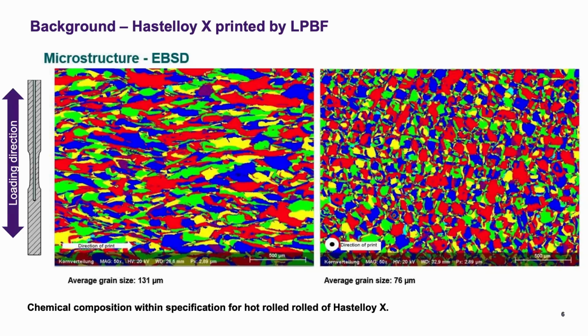Okay, and this is just to show you the loading direction of the specimens that were tested. I mean, we had a limited test scope, so we were forced to select one loading direction, and then we went for what we thought was most critical, the transverse direction to these columnar grains.